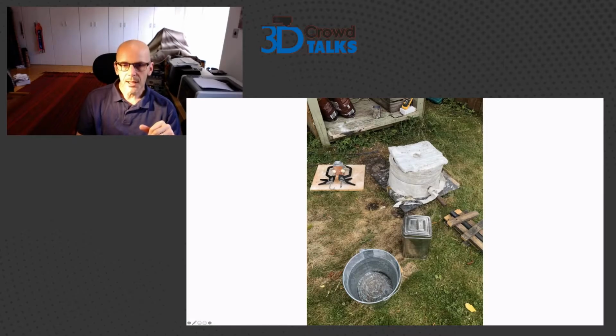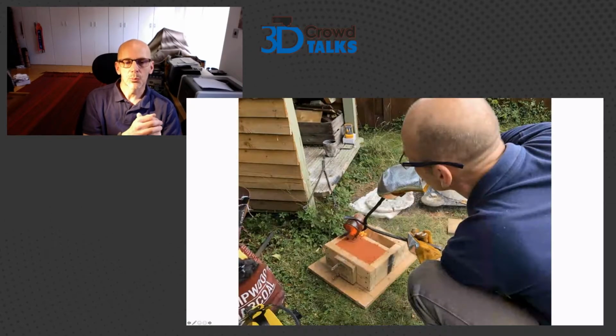So we're ramping the heat up, and then this is bronze, so it's about 1,000 degrees. I'm using tongs, and as you see, all safety devices, special aluminized gloves there to protect from the heat, because it really does feel very hot. Even on a cold day, it radiates heat towards you. Lifting that crucible up with the molten metal, and it's quite a magical process of actually pouring that then into this mold, which partly burns the sand, but it very quickly wicks away the heat. So then putting the crucible out of the way